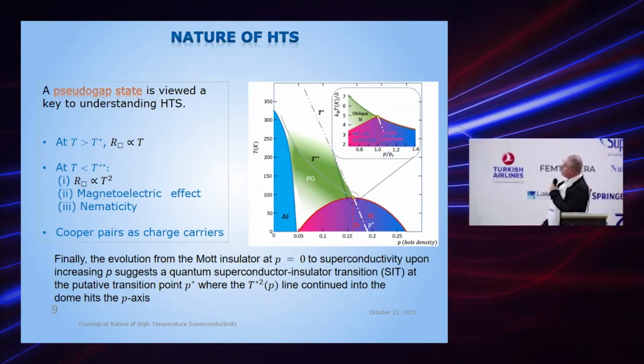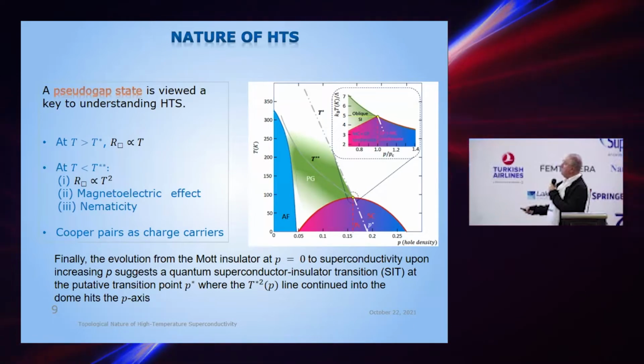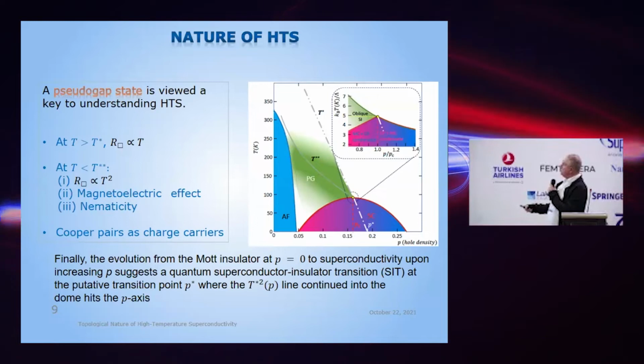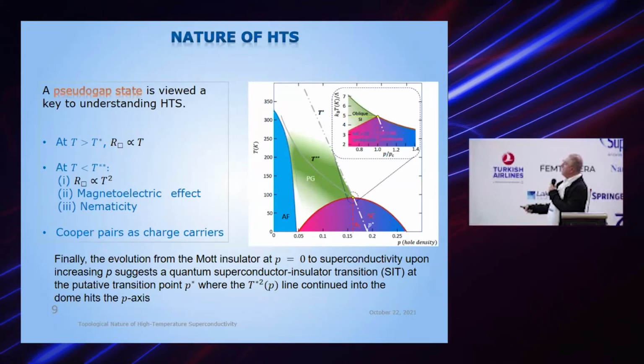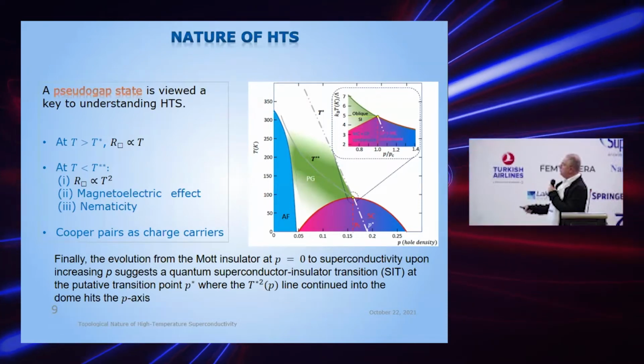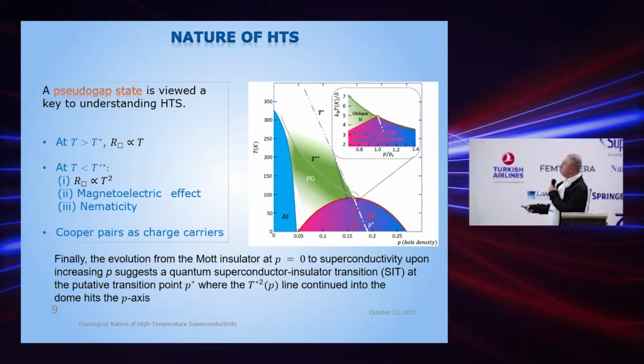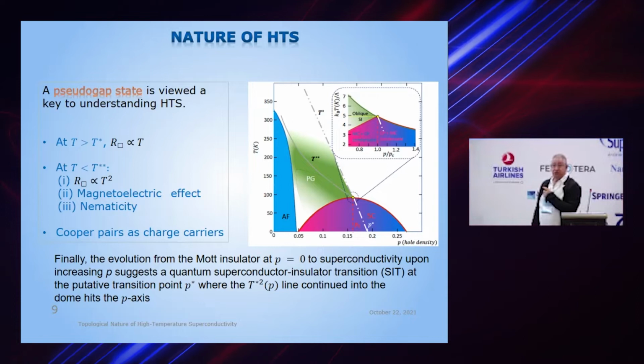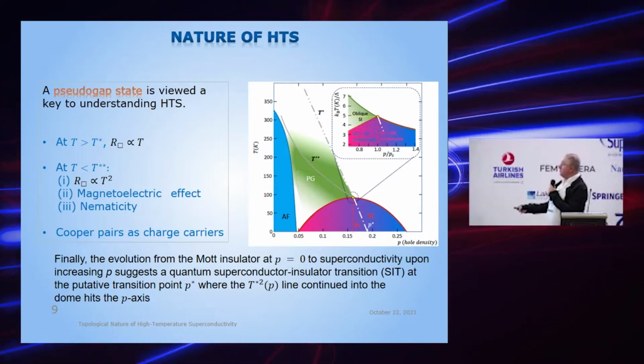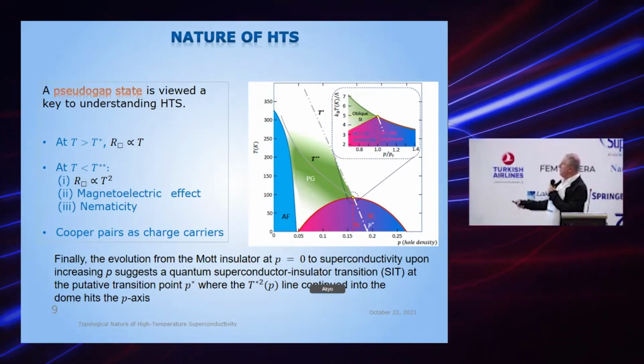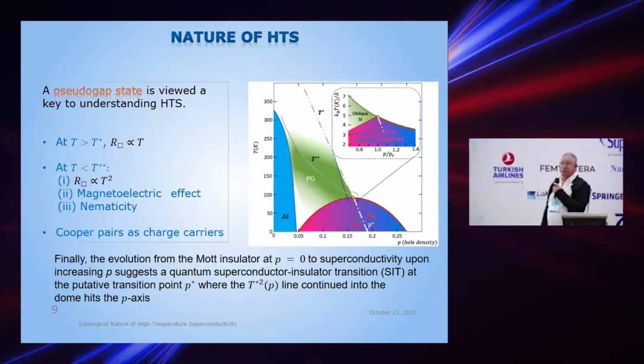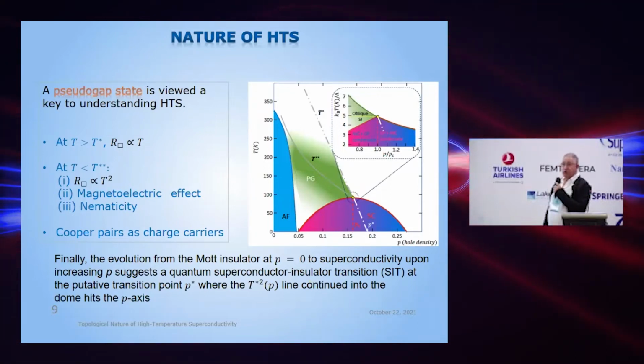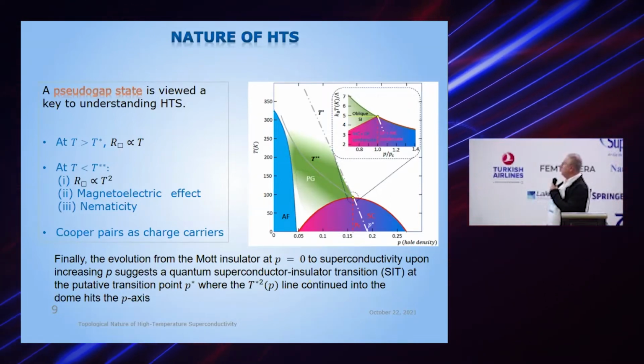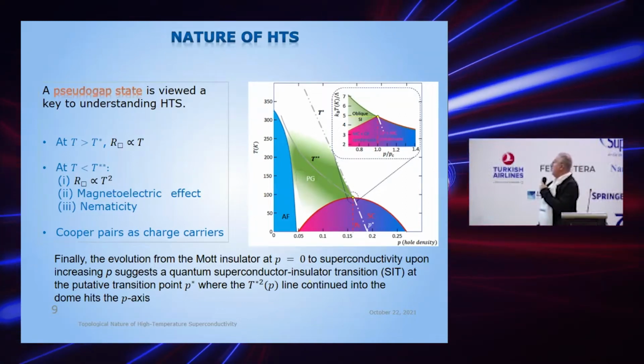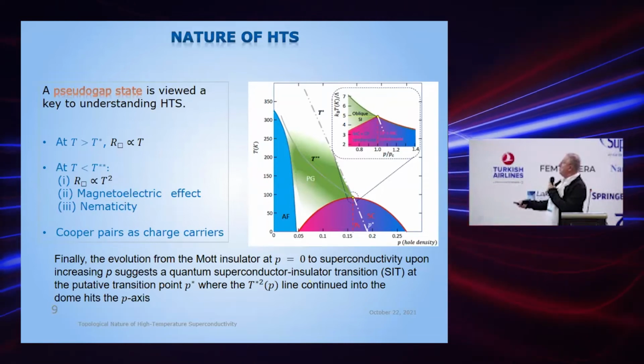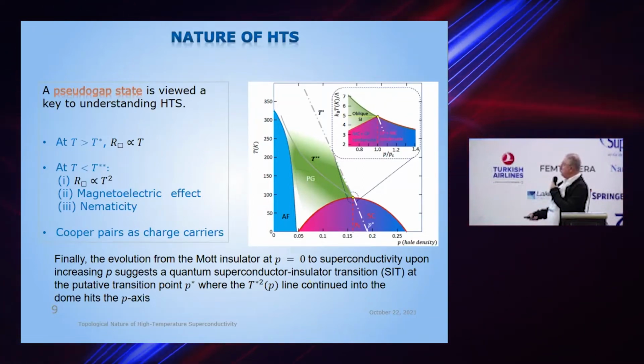So one of them is this Fermi liquid-like behavior, which appears in this region when the pseudogap state is fully established. Then there are nematicity and magnetoelectric effects, which don't find an explanation. Then another thing, which Ivan mentioned yesterday, is that charge carriers, even in the pseudogap state, are probably Cooper pairs because they carry the charge 2e, as he established by beautiful noise measurements, and it's still not quite clear why it should be so. And so we start with this, and then we will try to resolve all the other problems.